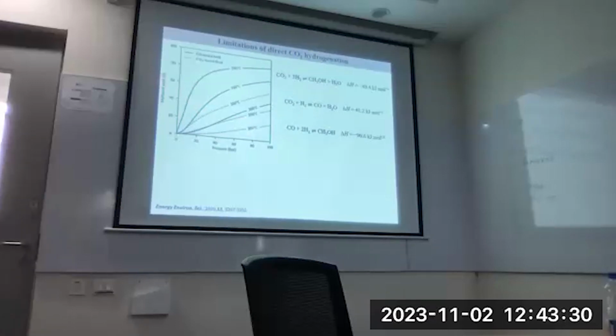The methanol yield decreases at a higher temperature because you end up making this reaction happen instead of this one, which is an endothermic process and is favored more at higher temperature. Sometimes it forms methane also. So in CO2 hydrogenation, the maximum methanol yield you get is around 40%, and the conversion is not that good. It's at 250 degrees that the conversion is ideal.